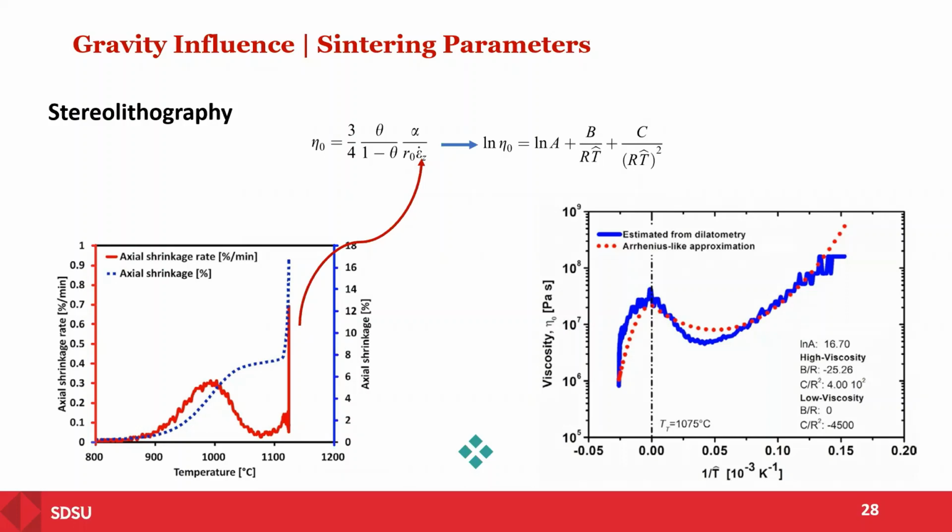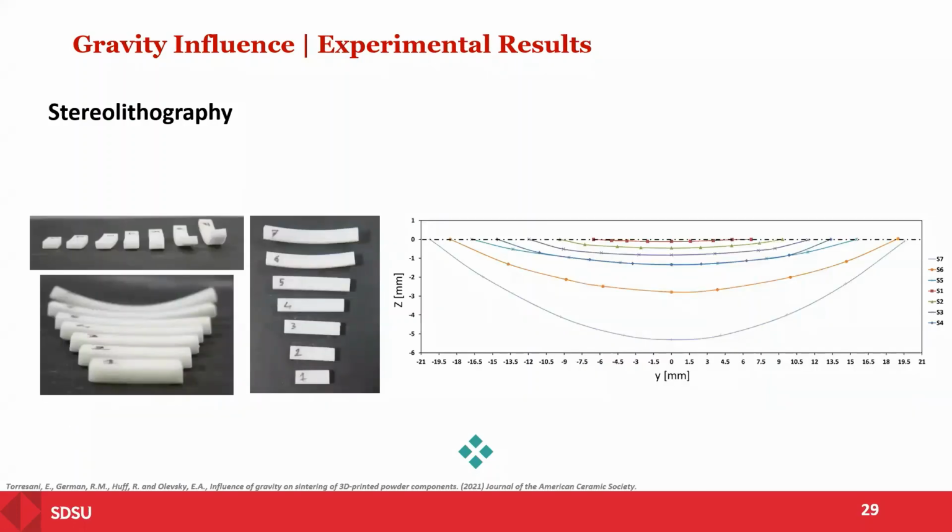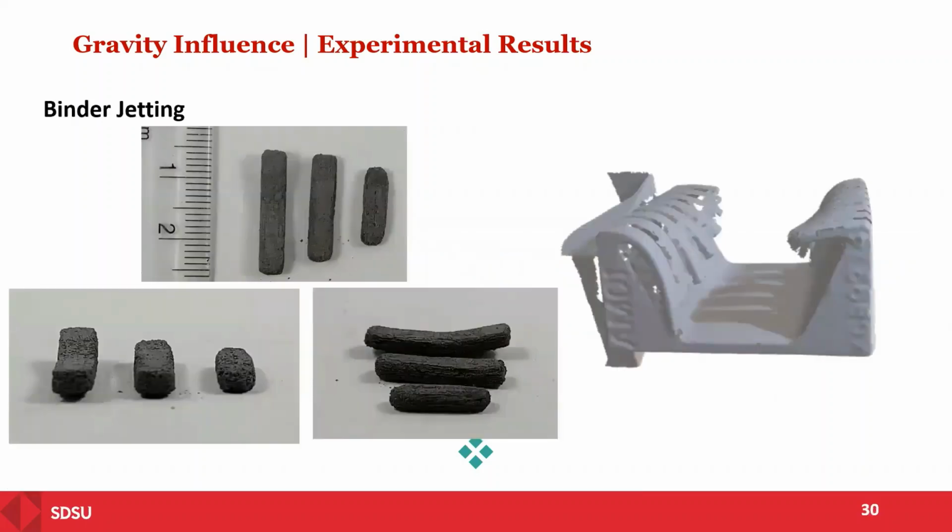Knowing that, this is from the experimental data, you can see how these beams bend as a function of the length. Also, for the metallics, some of them, the longest ones, are not present because they just crashed, they just broke. But here is, as I mentioned, the 3D scan of that part I showed at the beginning. You can see how heavily distorted those beams are.